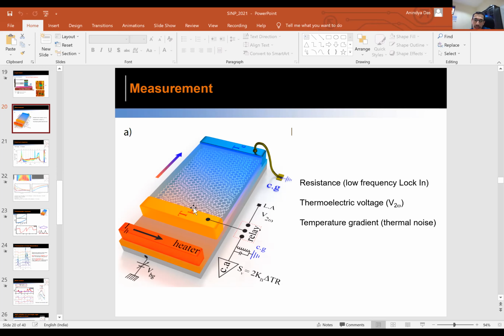And again, the temperature difference across these interfaces, there is nothing. And for the thermoelectric voltage, at the end, you measure the voltage V2 omega throughout the sample. Now you can write in that V2 omega some series combination coming from the contact, the channel, and another contact. Now I'm saying that around this contact resistance, your temperature difference is almost zero, right? Because it's a single line. So as a result, that will give me a very small, negligible amount. We believe that probably is not playing a big role here.